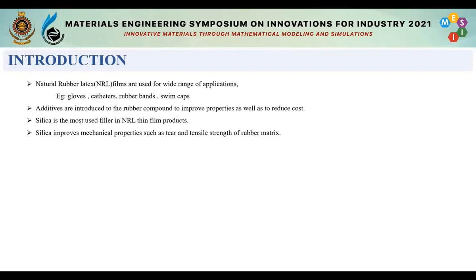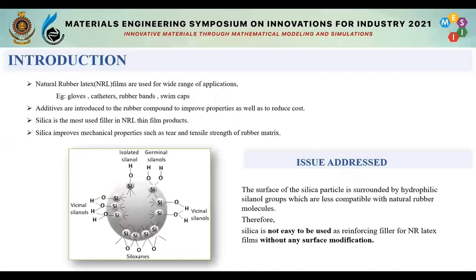It is a known fact that silica improves mechanical properties such as tear and tensile strength of the rubber matrix. But the issue in incorporating silica into the rubber matrix is that silica particles are surrounded by hydrophilic silanol groups, which are less compatible with natural rubber molecules, which are hydrophobic in nature. Therefore, silica is not easy to use as a reinforcing filler for natural rubber latex films without any surface modification or assistance of any other dispersing agent.